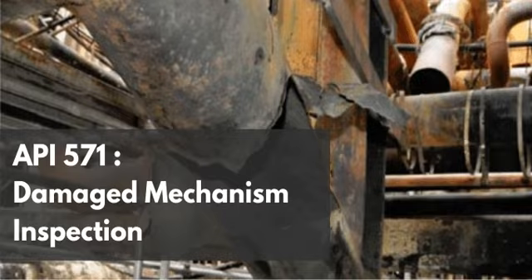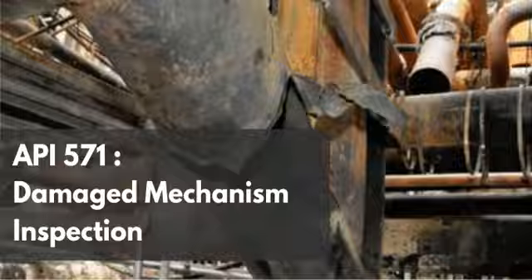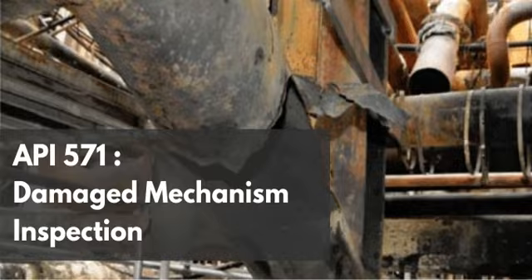But a crack is just a linear indication on an NDT report until you actually prove what caused it, right? I mean, other mechanisms like wet H2S damage or thermal fatigue can produce cracking near welds, too. They absolutely can. Which is why the text mandates metallographic confirmation for a positive diagnosis of Amine SCC. Okay, so what is the exact microscopic fingerprint we're looking for when we put a core sample under the lens? Well, you have to look at the crystallographic structure. The text outlines 3 mandatory characteristics for positive identification.